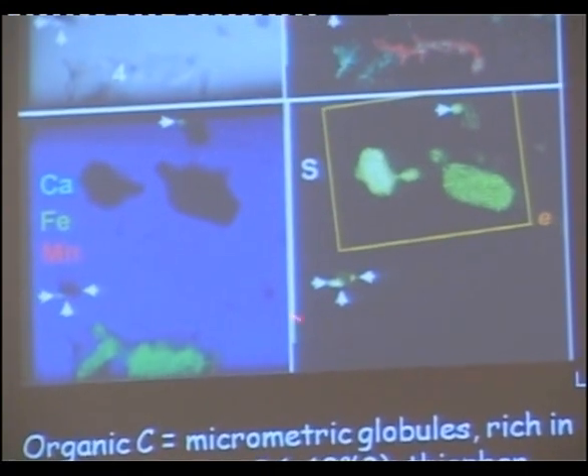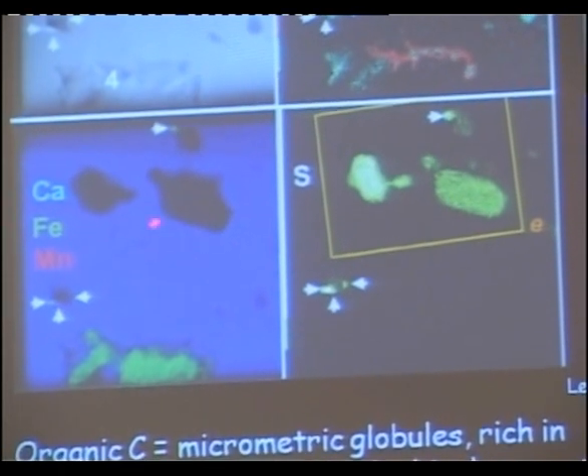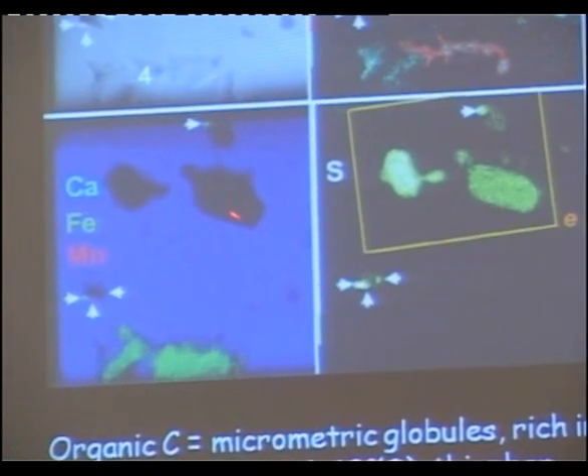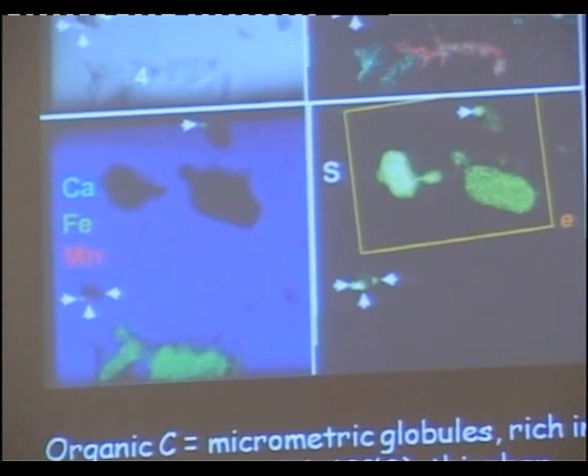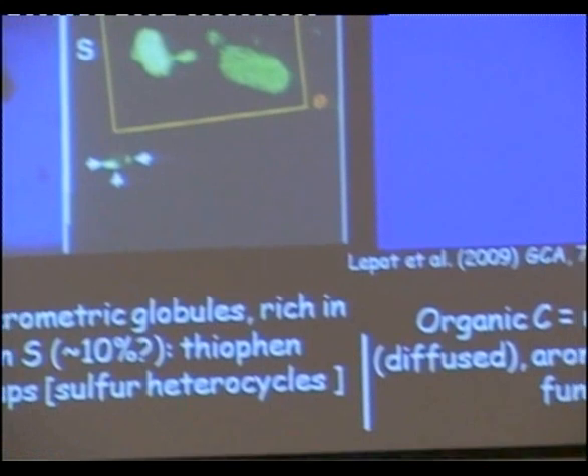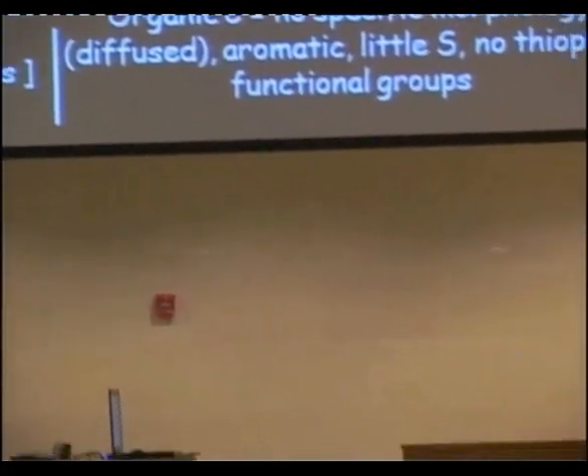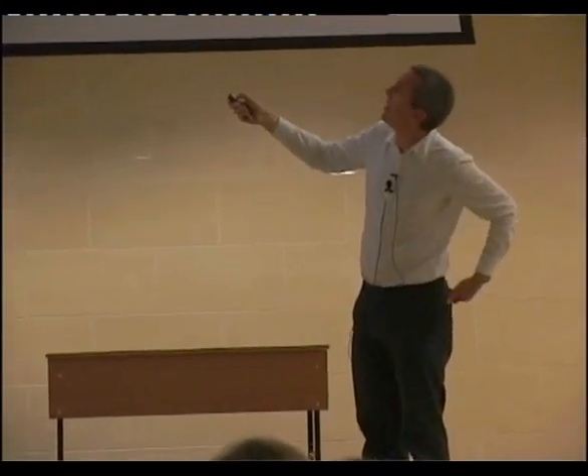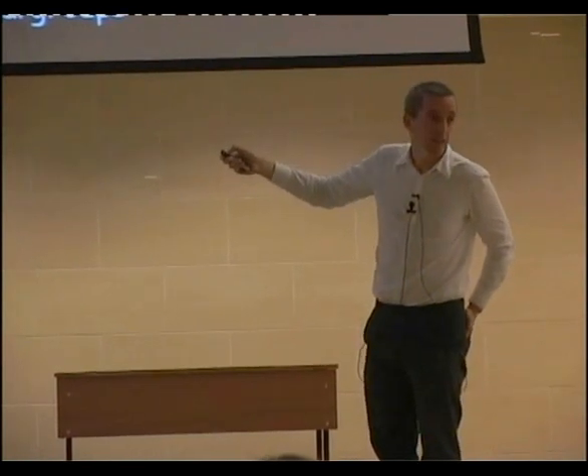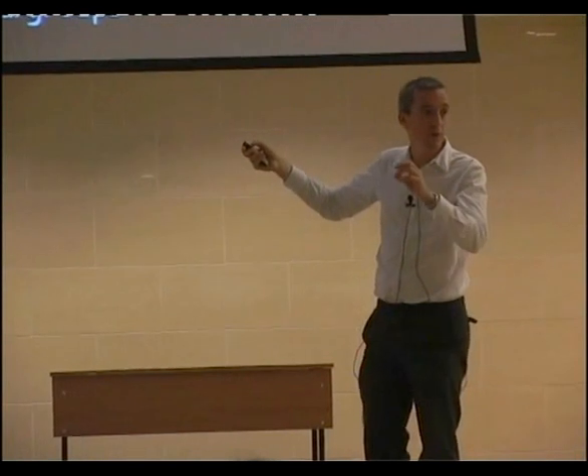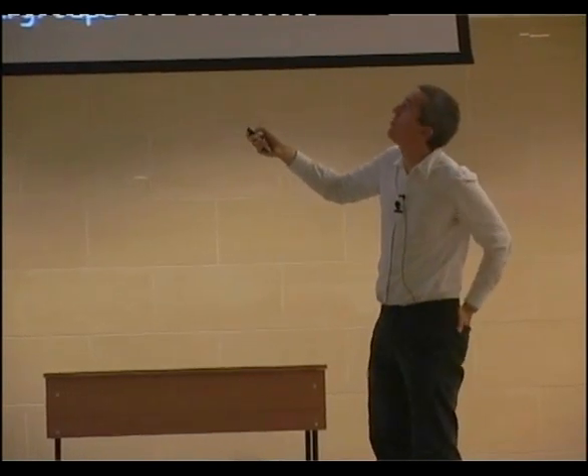This is not iron sulfur. There's no iron. This is the iron map. You see here, there's no iron showing up. So this is sulfur associated with the carbon. We have spectroscopy data that shows that really this is organic sulfur. So the organics within the carbonate laminae is sulfurized. There are some organic functional groups composed of sulfur.